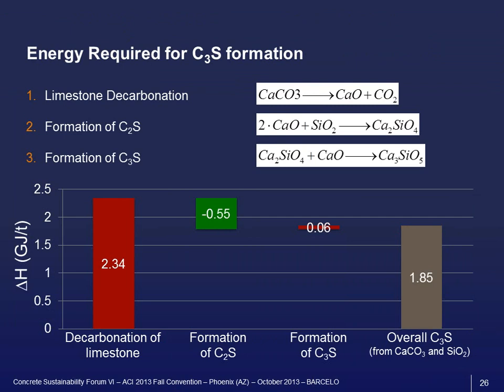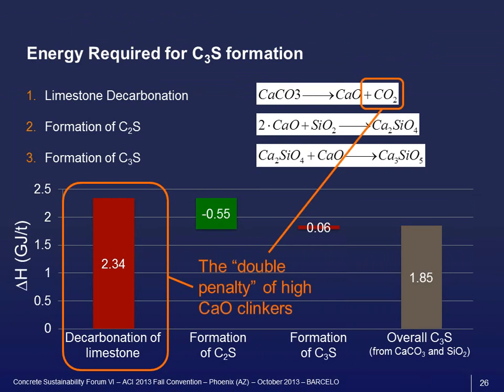So you can see here the double penalty with high limestone cements. We have a high amount of CO2 released by the decarbonation. And we have to go through this massive energy consumption for the decarbonation that translates into fuel. So double penalty for high lime system.